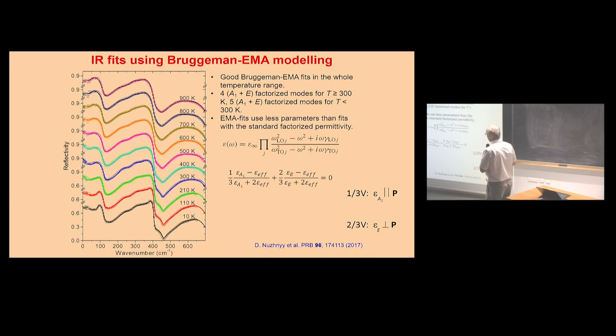And we tried to understand it. So we measured infrared spectra, quite complicated here, but from 10 Kelvin to 900 Kelvin. In the case of cubic structure, there should be only 3 polar phonons given by symmetry. But finally, you see more bumps, that means more polar phonons, due to the fact that in polar clusters you have broken centrosymmetry, and also you have distortion of lattice.